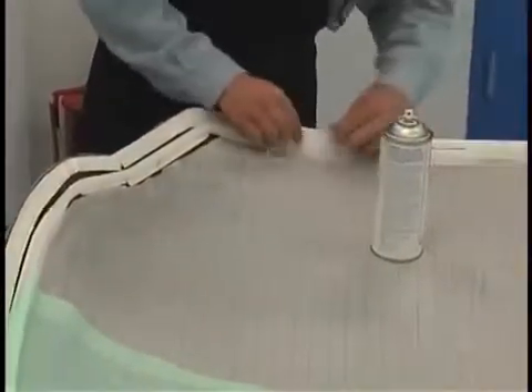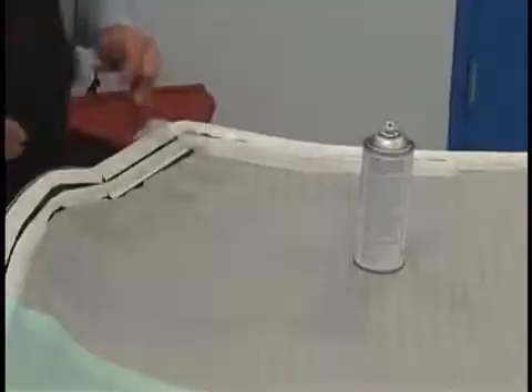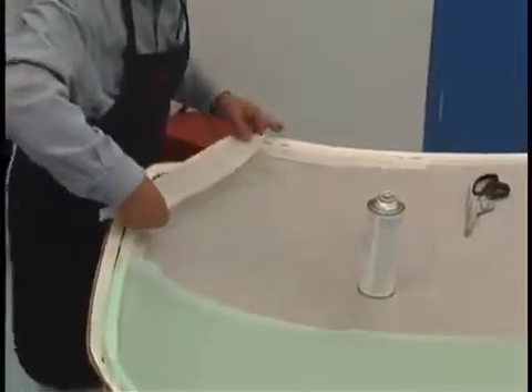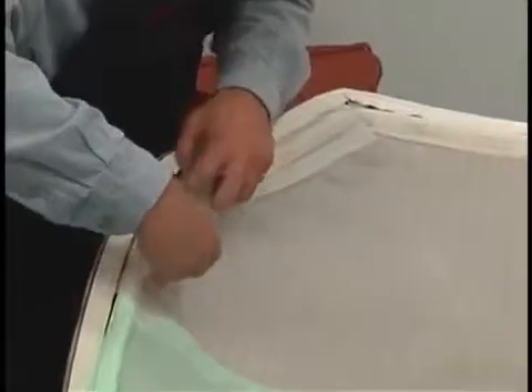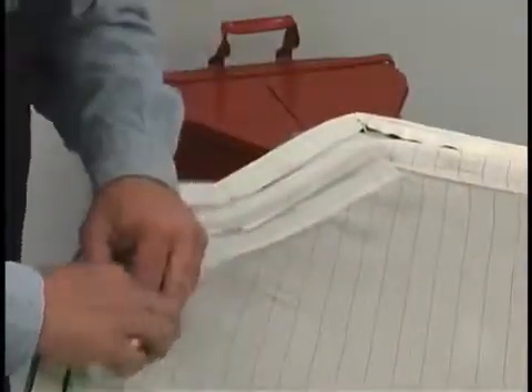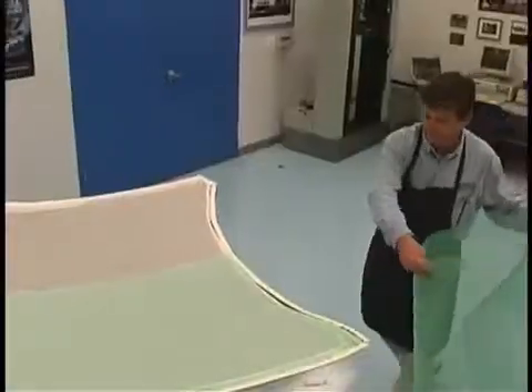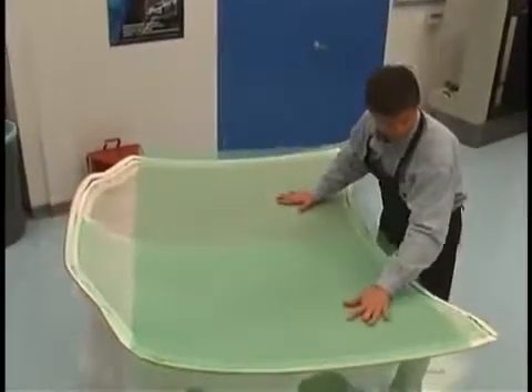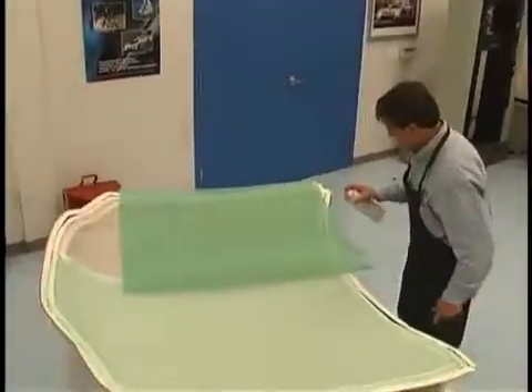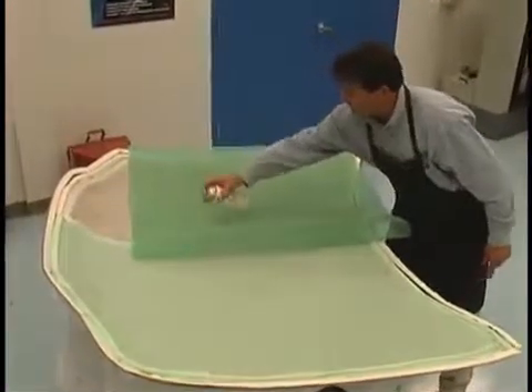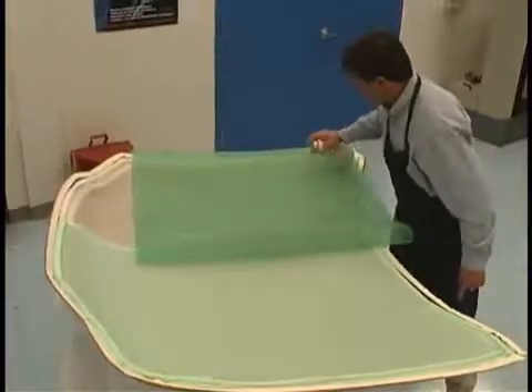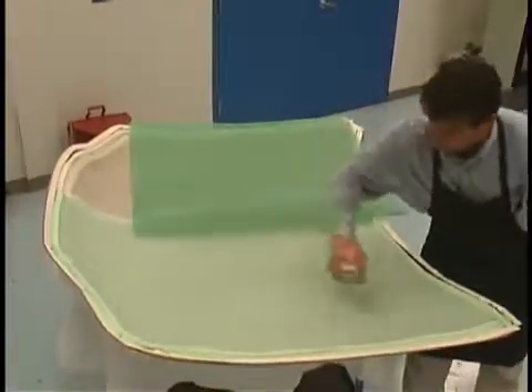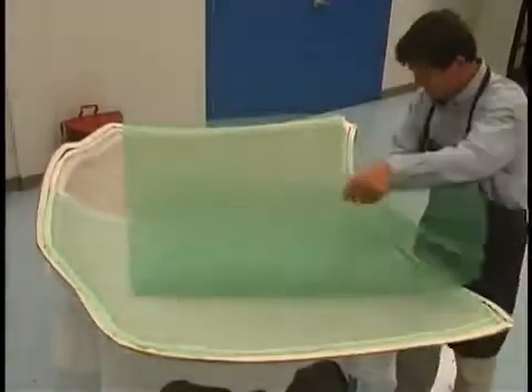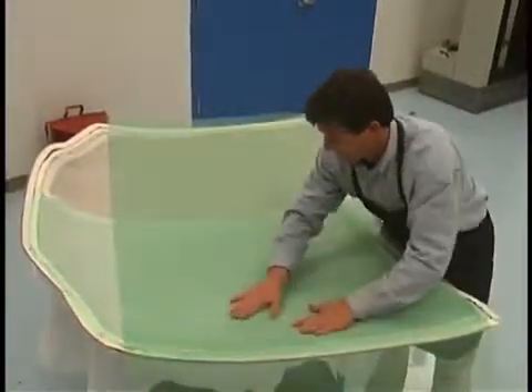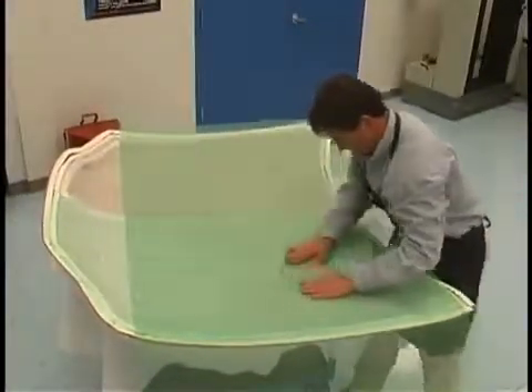It is important to trim the peel ply so that it does not later interfere with placing the vacuum bag against the sealant tape, which could cause a leak path. Next comes the placement of the resin flow distribution media. Here we are using Airtech's Green Flow 75. This mesh is held down using our spray adhesive and trimmed just inside the spiral tubing. The flow medium provides an efficient method for distribution of resin across the part surface.